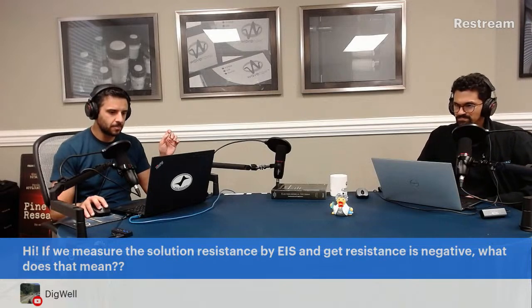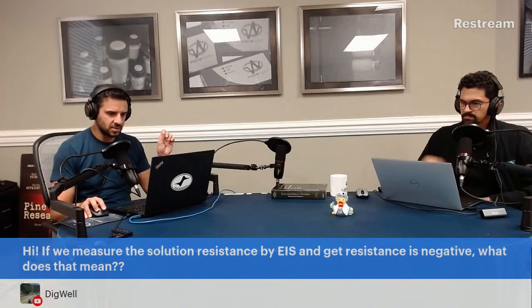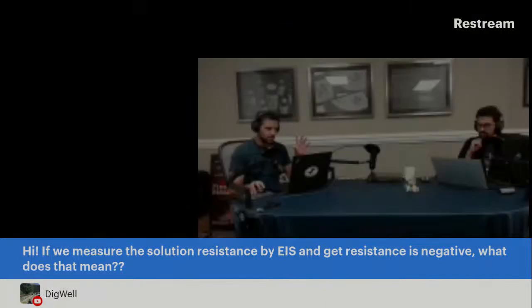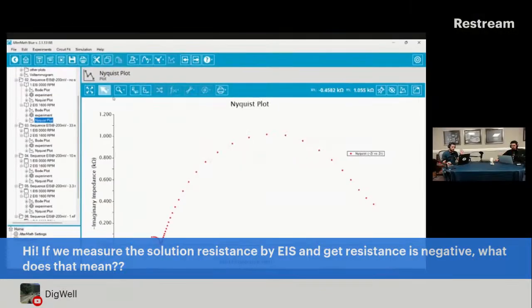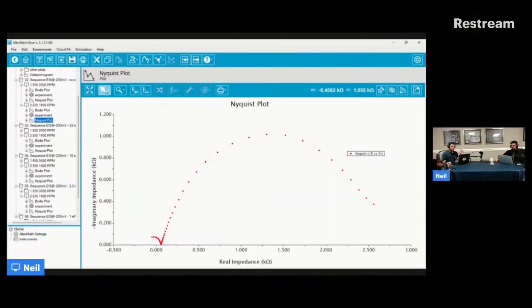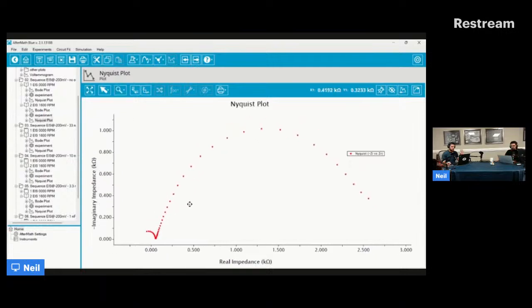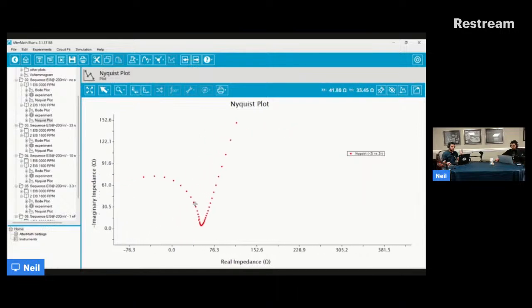So many times when you are studying systems that give you a sort of odd behavior at high frequency, you get something that looks maybe a little bit like this. So you might have a Nyquist plot and at the highest frequencies, all the way on the left here, it starts to veer into negative territory. Or you have a semicircle that doesn't complete, but if it did, it would complete in negative Z real. See, this is the Z real down here. It's odd to see.